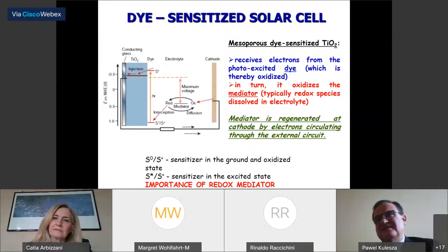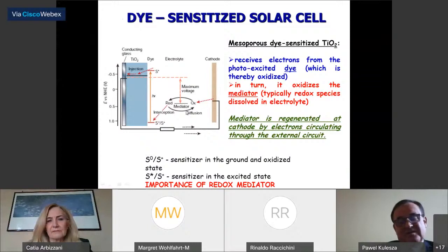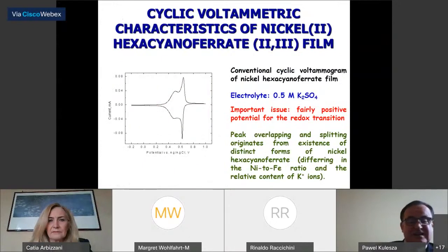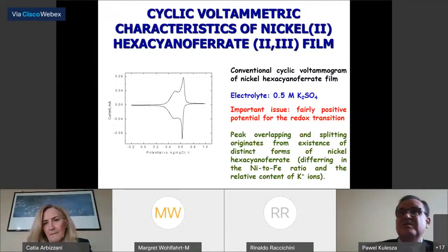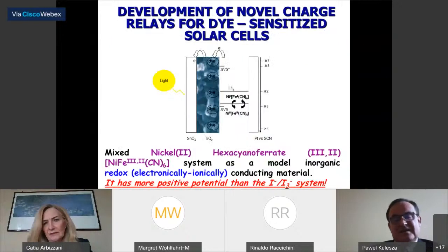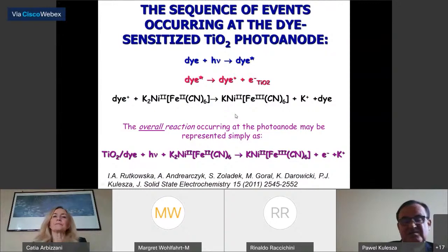So we went to the dye-sensitized solar cells, actually the work of Iwona Rutkowska. And metal hexacyanoferrate in mixed form could serve as a redox mediator and help upon injection of electron to the conduction band of titania covered with a dye, we can make a cycle by using the redox mediator. And the crucial part, interesting, is that nickel hexacyanoferrate has a relatively positive potential, much more positive than the iodine iodide couple commonly used in the systems. And if you look on the scale, we are more positive, so the potential output coming from this type of system should be better. And indeed, it was.